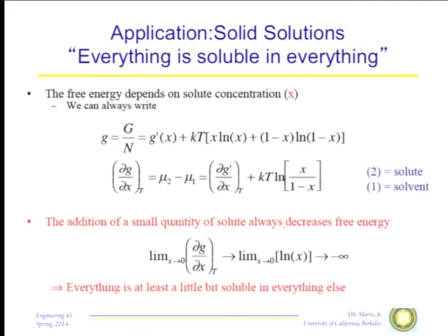Now let's take it to 0. There is no reason to believe, in fact, every thermodynamic model in the whole wide world will tell you that this term is perfectly well behaved as x goes to 0. So we can ignore this. However, look at this term. You know what the logarithm of 0 is? The logarithm of 0 is negative infinity. And that's telling you that the very first little tiny bit of solute you add to the solution is going to drive the free energy negative, and it's going to do it in a really big way.